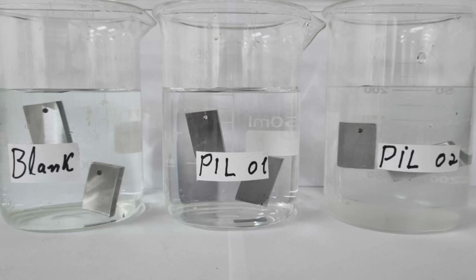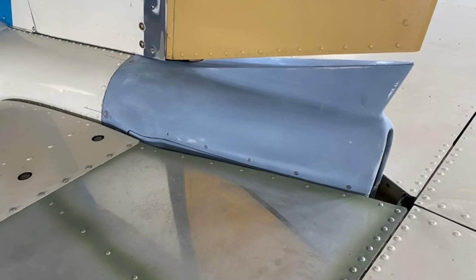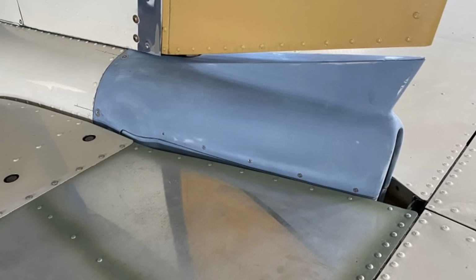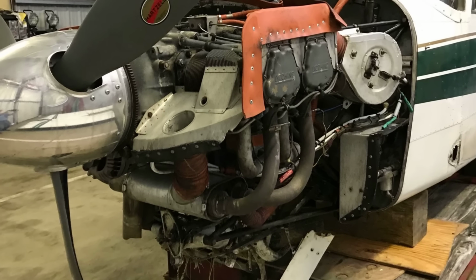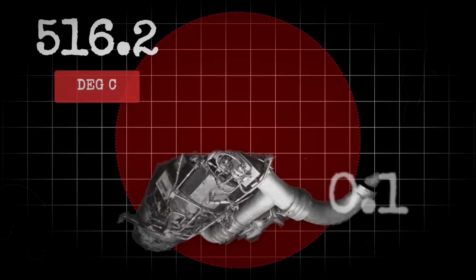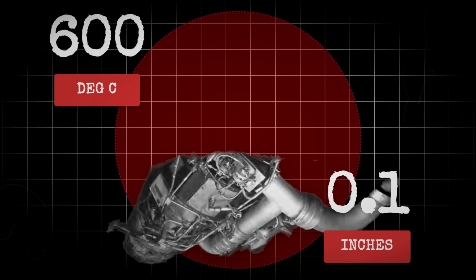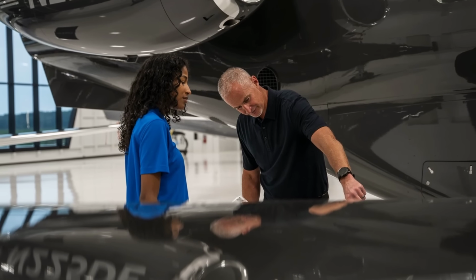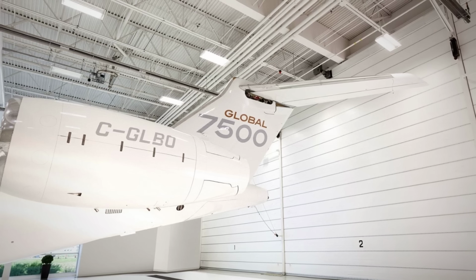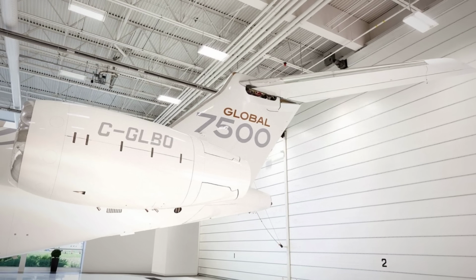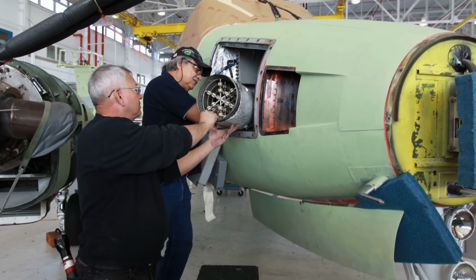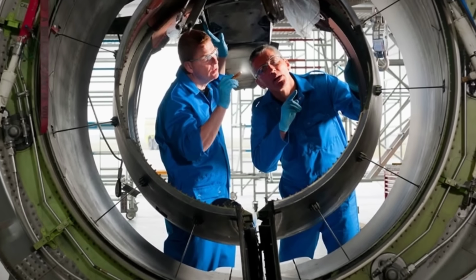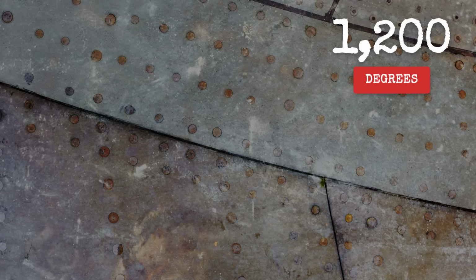The chemistry is brutal. Acidic exhaust breaks down the last layer of primer, and the aluminum starts to pit. Over time, the corrosion goes deep, eating away at the beam from the inside out. There is no easy way to spot it from the outside. No bubbling paint, no obvious stains. The only way to know is to pull the nacelle panels and run a chemical swab test. If the swab comes back with a high chloride reading, you are already in trouble.